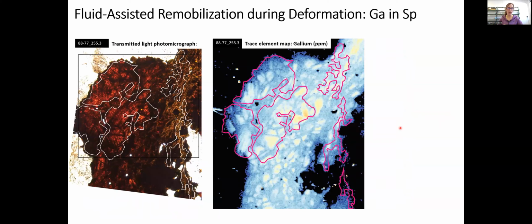Now, I've started work on trying to actually quantify the compositional changes like this, using software called XMapTools, highly recommend, really cool. You feed in your compositional maps, and you can outline different areas like I've done here, and then extract all the analyses within them. So in this case, I've outlined some coarse sphalerite. Heads up, this is including several grains, so it includes several grain boundaries. And I've outlined areas of fine-grained recrystallized sphalerite, which by necessity includes grain boundaries because they're just so fine-grained. The really funny shapes are because I'm avoiding inclusions and holes and trying to get as pure sphalerite as I can.